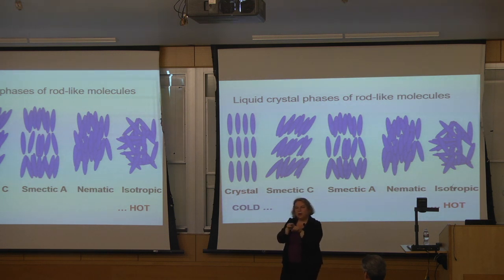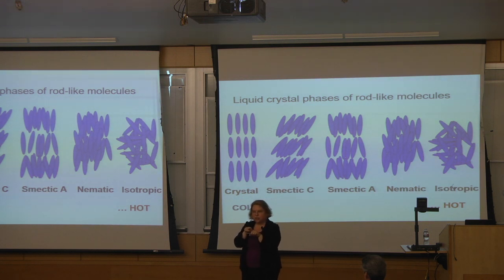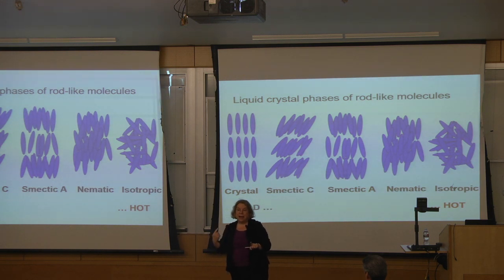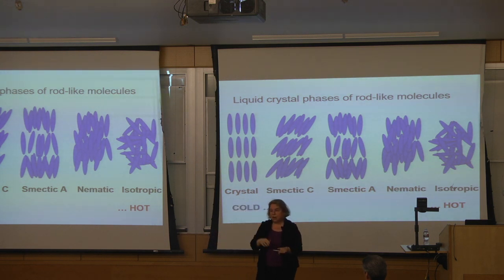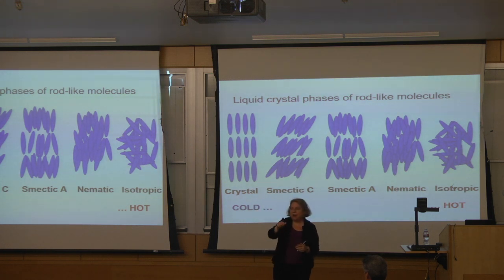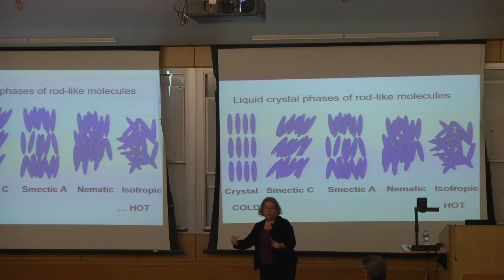You can boil your rotini just briefly to soften it up a little, and then take a needle and thread and go sideways through the rotini and put a whole bunch of them on a string. And you know what they'll do? They'll make a spiral. Okay, so in a cholesteric liquid crystal, if the molecules are chiral, you will get a twist. So that means the long axis of the molecule is locally parallel to its neighbors, but over a distance of, say, microns, it will rotate. Okay? And it might be that if you have a material that's not chiral, like these nice smooth round rods, they're not chiral at all. But you can add a little chiral dopant, a little chiral stuff, and it will induce the twist.